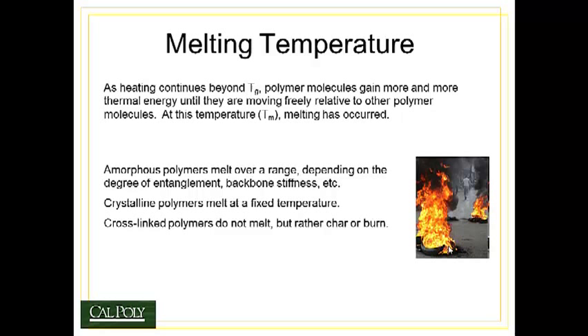Beyond the Tg, as we continue to add heat, we eventually arrive at the melting point of the material. Here the polymer molecules have gained so much thermal energy, they're now able to freely move relative to one another within the polymer melt. But keep in mind that not all polymers melt the same way. Amorphous polymers melt over a range of temperatures, and this depends on how much entanglement there is, the backbone stiffness, molecular chain length, etc.